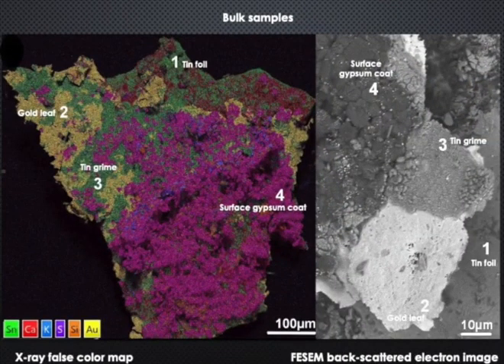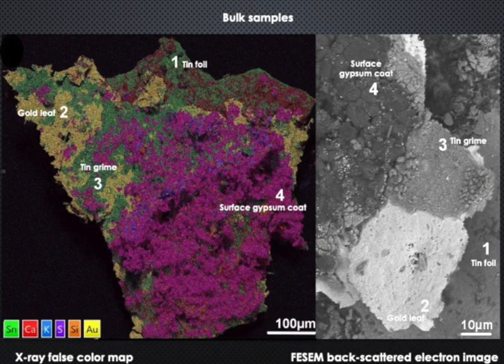The gilded tin structure and chemical composition are shown here. Note that over the gold leaf, a new layer is formed made of tin corrosion compounds — hereafter referred to as grime — which is covered by a gypsum coat at the surface.